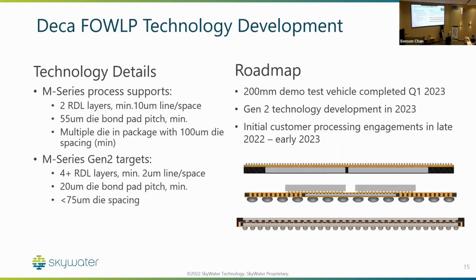So a little bit on the roadmap for that. The M series process today, if you're not familiar with this, supports 2 RDL layers and a minimum of 10 micron line space, 55 micron die bond pad pitch in the package. So the devices themselves that are integrated have 55 micron pitch, 100 micron die spacing.